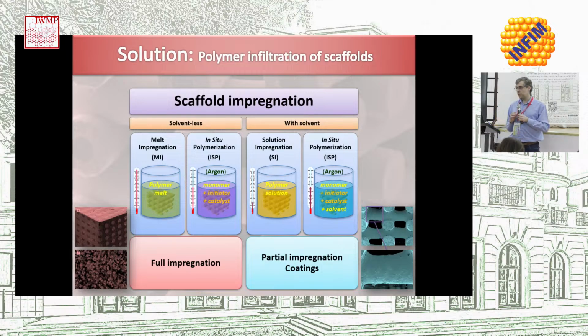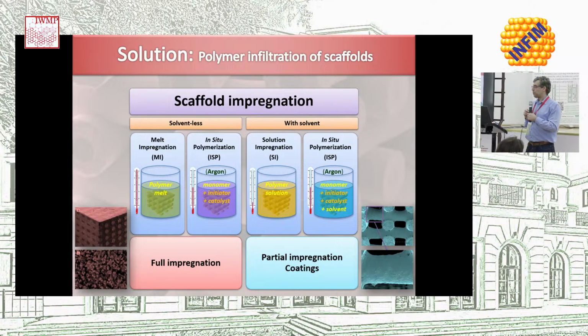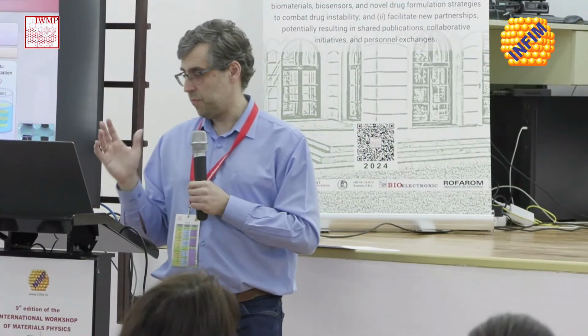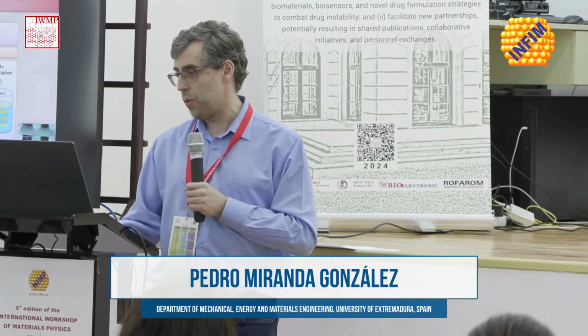So Antonia mentioned already that we can produce that by polymer infiltration. Either we get fully dense structures that can still be used as scaffolds, because if you select a polymer which is biodegradable, you could produce the porosity in situ. That's possible. And even if they are not scaffolds anymore, they could still be used for fixation devices, which are dense. So that's another possibility for using the fully impregnated structures. Or we can preserve the porosity and get only coatings that will heal the defects on the struts, but also keep the macro porosity that we defined, so we can still get bone growth and so on.